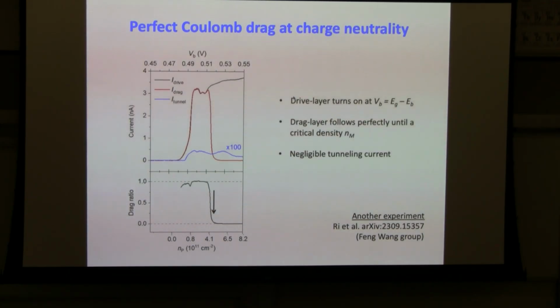You can think of it this way: if you want to drive a charge current, you need to apply an in-plane electric field. But if you want to drive an exciton current, in this dipolar case, you want a displacement field gradient in the vertical direction. Okay, let me rephrase the question. There's a physics thing I'm not getting, which is that this is neutral transport, but you're measuring with charge transport. Yes. And so there's an unstated thing going on where the excitons form and unform at the edges or something. Yes, at the contact, yes.